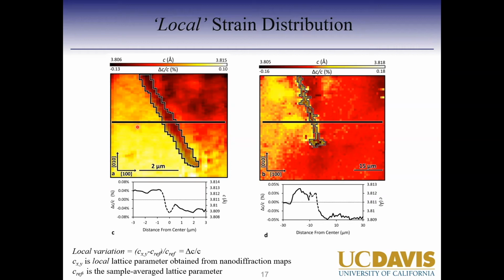And interestingly, we measured quite a bit of filaments. I think about 7 or 8 filaments for different samples. And we always see this interesting switch where on one side of the filament your material has, let's say, positive strain. So this is a line scan taken across this line shown here. You have positive strain, and across the filament, it switches to negative. And same for filaments which are even as long as 50 microns, we still see the same switch. So it's almost as if filaments are growing in the areas where there is a strain gradient, or they're growing to give that strain relief in the material.